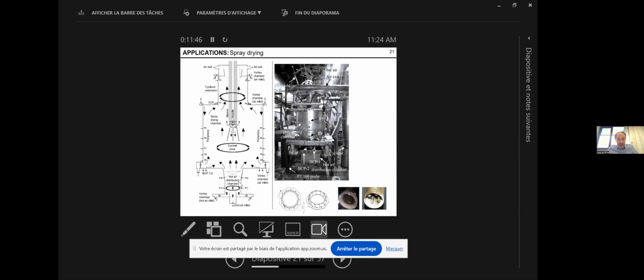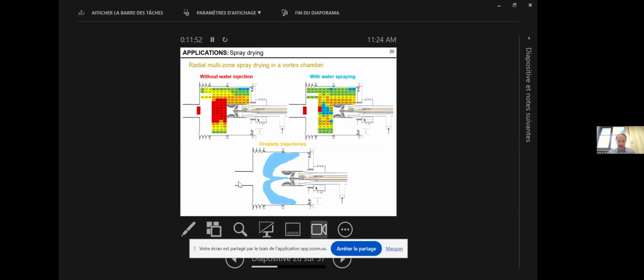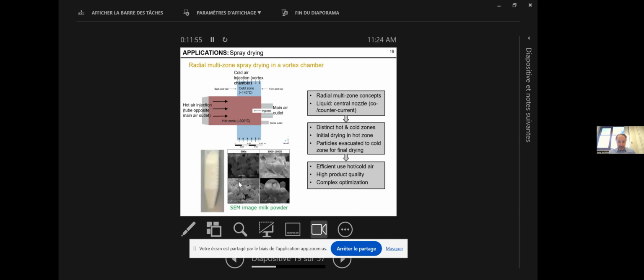Sorry, let me explain the concept here on this slide. Yeah, on this one. In a radial multi-zone dryer, we have again drying in 2 steps. Fast initial drying in the radial center, and then final drying simply in the periphery. The idea is to have a fast evacuation from the central zone to the periphery thanks to the centrifugal force. Yeah? And so in this central zone, how do you generate the centrifugal force? By injecting this mild temperature air in the periphery through vortex chambers.